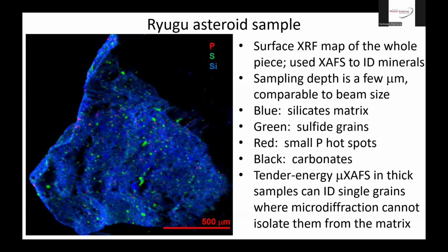So in this image, blue is silicon, so the silicates in the matrix of the material is blue. The green is sulfur, so those are the sulfide grains. And the red, there are small hot spots of phosphorus. There are some black spots showing on that, and those are carbonates that don't have any of those three elements. So typically we'd map a sample and then do the microspectroscopy at different selected locations to see what's there.